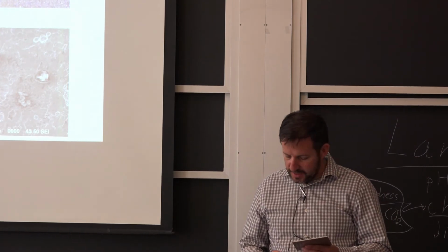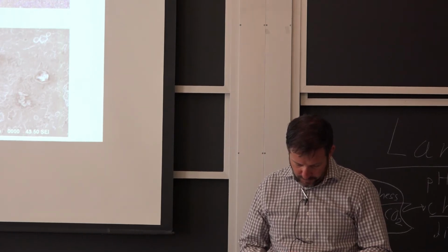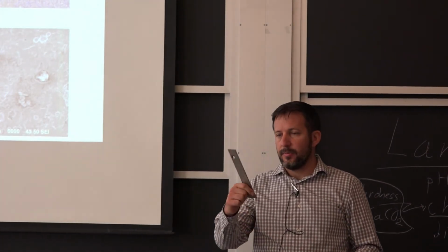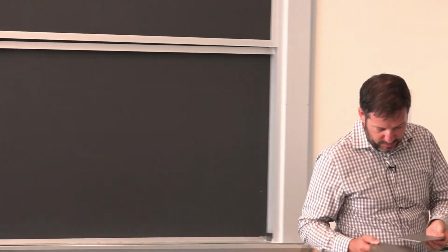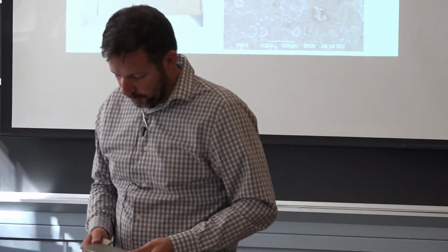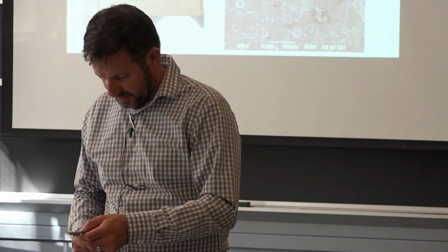So in the case of stainless, this was a very fancy home that we were asked to consult on. It was built, and within literally 2 months, instead of being a super nice finish, it looked like this on the outside. So quite terrible from an aesthetic standpoint. Be fine from a structural standpoint, and what they were looking for was something like this. So I'll pass it around. This one is actually not the original. So this is what comes out of the mill, and that wouldn't corrode. This is what we did as a refurbish or repair. This was another repair that didn't work, and this is exactly as installed.